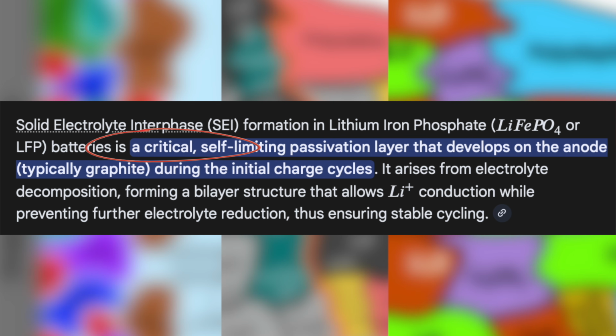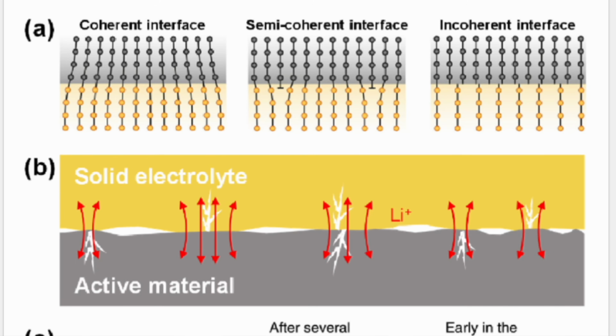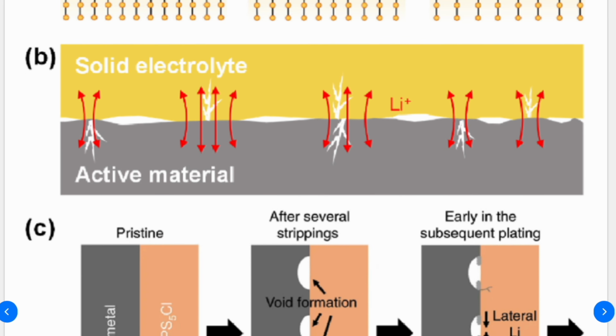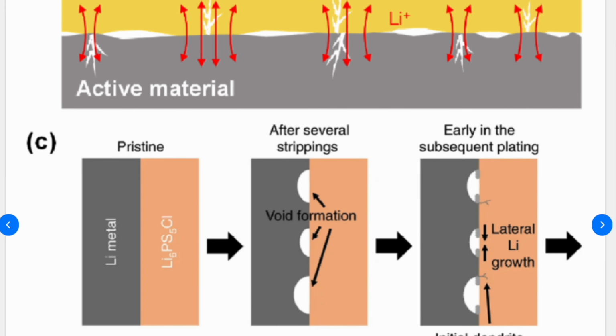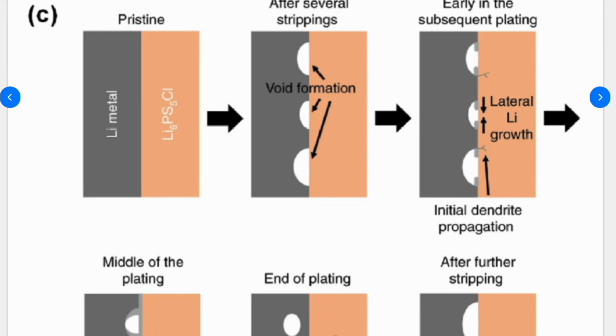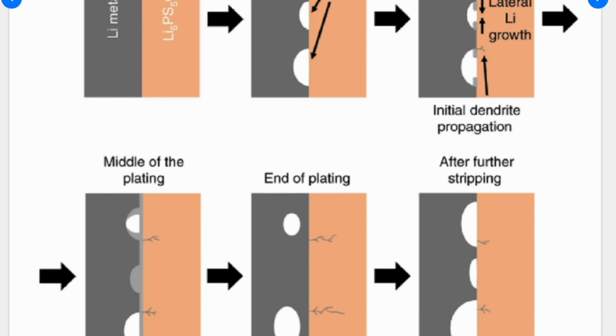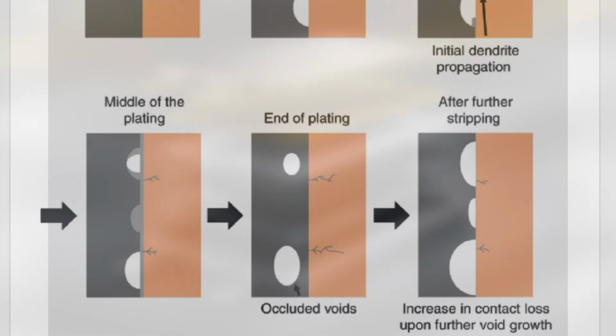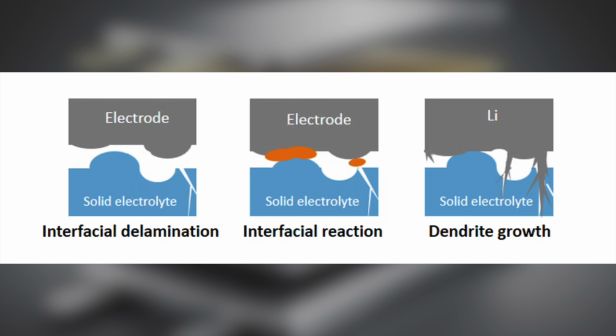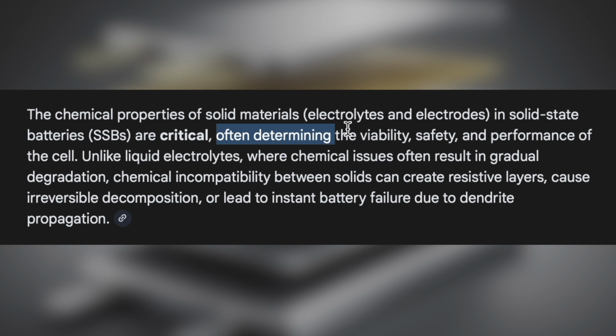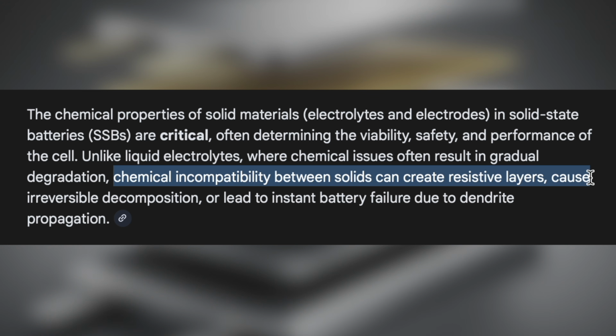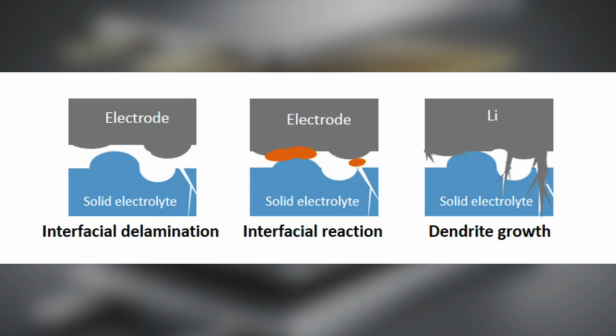But with a solid-state battery, layers of this type can form over time as solid electrolytes can react with the electrodes themselves. These layers can reduce conductivity, grow brittle, and create fragility within the battery, as well as reduce the life of the battery over time. And the layers often continue growing during additional cycling. And since there's no liquid electrolyte, the mechanical properties of each solid become critically important. Differences in stiffness, fracture behavior, and thermal expansion mean that interfaces between materials become hot zones for failure and degradation. And these interfaces can provide pathways for dendrite growth along defects or cracks.